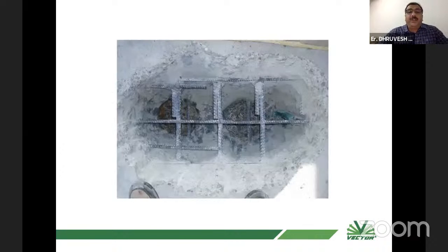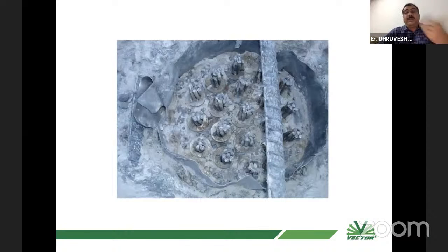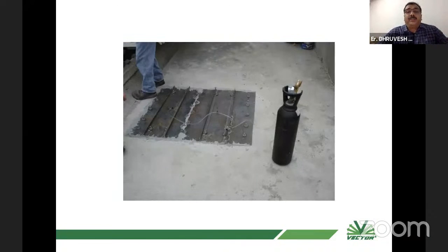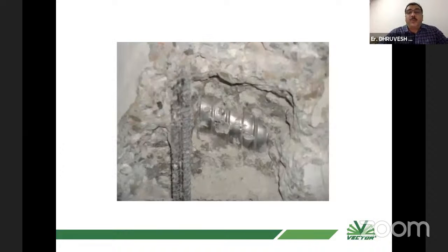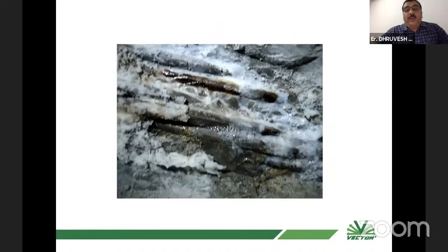This is one of the bridges where we did the moisture test by passing the gas from the other side. It was sealed and a small amount of dry gas was injected inside, and the sheath was opened up. Actually, this is a video, I couldn't run it, I don't know why, there is some issue. So you can see this moisture and water coming out. We can visually see that the moisture was really coming out from the other end.